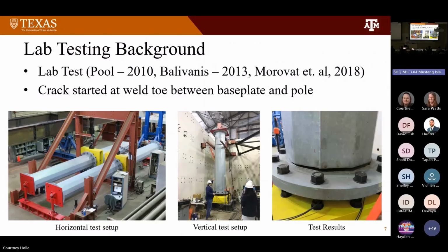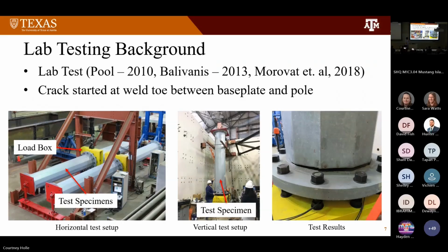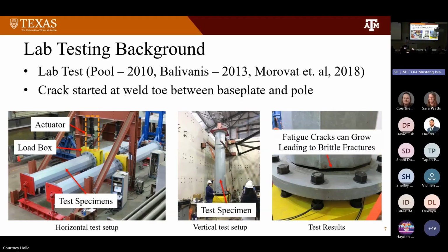To investigate this loading scenario under controlled conditions, many researchers have conducted experimental tests. Typically, this experimental test involves connecting test specimens to a load box and then applying cyclic loading through an actuator. And these results consistently show that fatigue cracks occur at the weld toe between the base plate and the pole and lead to brittle fracture.